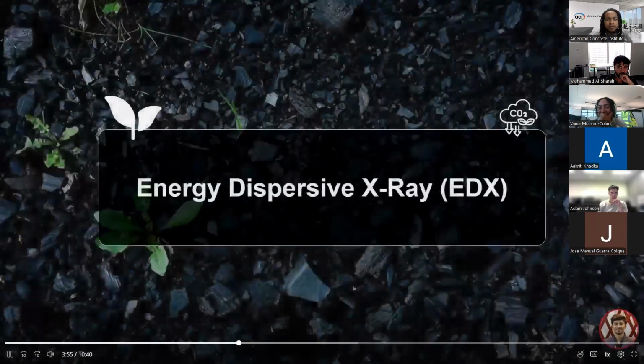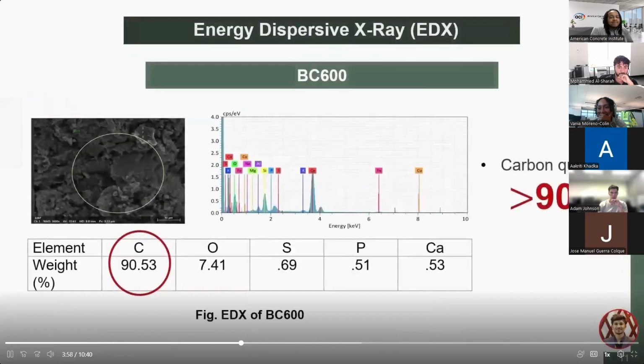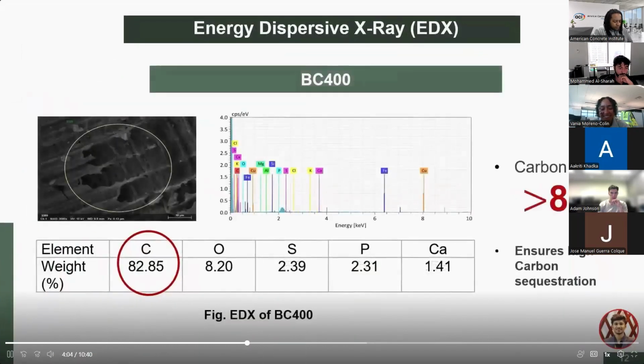In the EDX test results, we found that BC600 has a carbon quantity of more than 90%. On the other hand, BC400 has more than 80% carbon quantity. This percentage of carbon ensures higher carbon sequestration capability of biochar.